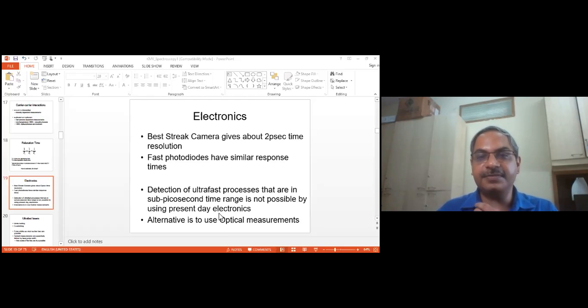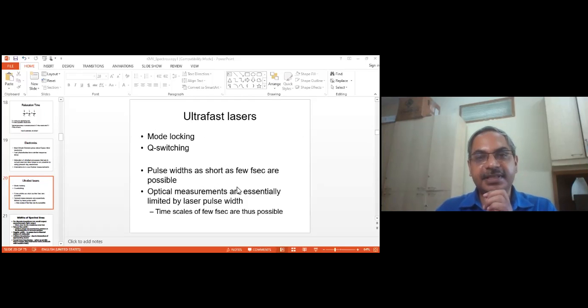Okay. So we use ultrafast spectroscopy because it can measure lifetimes or time scales which are only limited by the pulse width. And the shortest pulse width we can get now is 5 femtoseconds. So 1,000 times faster time resolution can be obtained if you go to optical measurements instead of using present day electronics. Okay, so for this you need ultrafast lasers. You may read, if you're interested, about mode locking and Q switching, how pulses are generated inside your lasers. You can get a few femtoseconds, 1 to 5 femtoseconds are all possible nowadays. Okay. So here the measurements are only limited by the laser pulse width. And so you can go down to time scales of a few femtoseconds by using ultrafast spectroscopy.